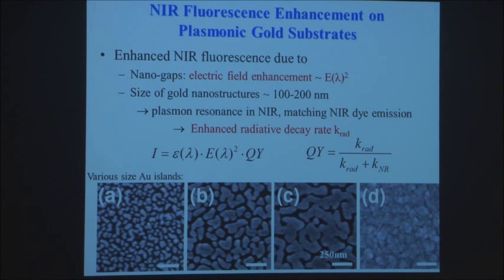So what's going on is that to enhance fluorescence, you want to have two factors being enhanced. One is the electric field. If you have a lot of small gaps between particles, your field gets enhanced, and that enhances your excitation of these fluorophores. So you get an E squared term there for the fluorescence enhancement. The second requirement we found is that the size of these particles, even though they're irregular, is on the order of about 200 nanometers or so, like these two. They enhance fluorescence because you get enhanced radiative decay. So the excited states of the fluorophore can emit light more efficiently, therefore enhancing the quantum yield and giving a brighter signal.